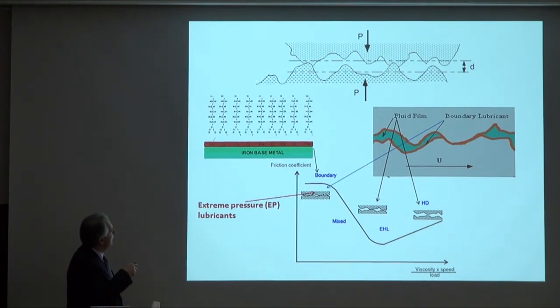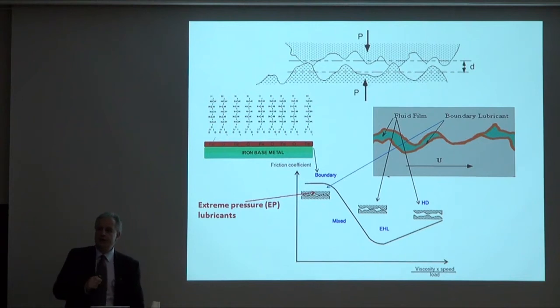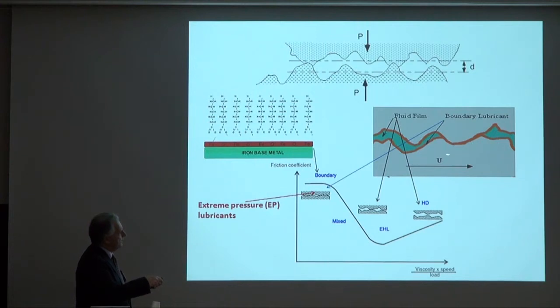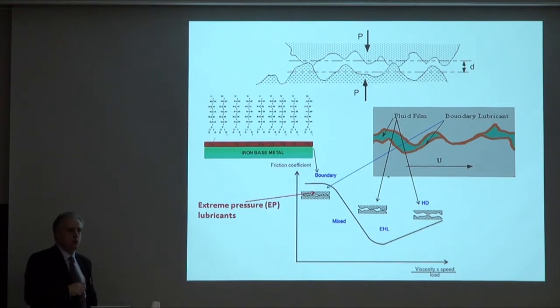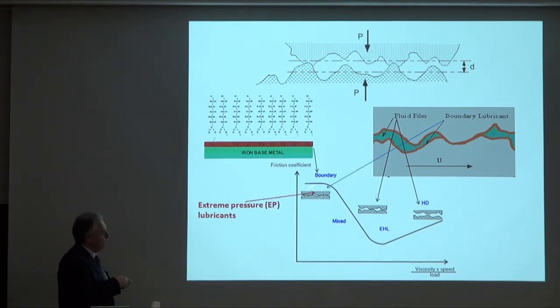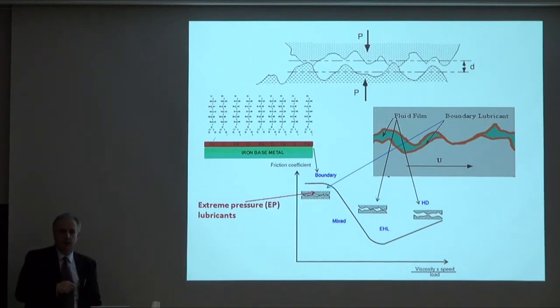And if we do not have an additive that will form this tribofilm between these two surfaces, as this orange layer here, in a case like that, we will have a strong tendency for the two surfaces to wear and adhere to each other. That is the reason why the friction coefficient increases, and that is the reason why we need the so-called extreme pressure lubricants, which will operate at these high pressures due to the surfaces being so close, to form these protective films, such as the one that is shown here by the adsorption of a hydrocarbon on an iron surface that actually has an oxide, since it's not a noble metal.